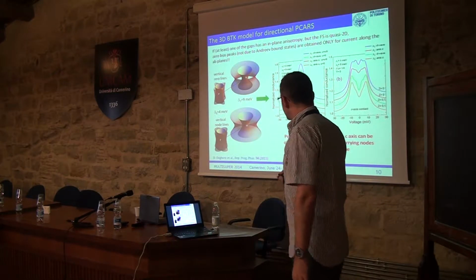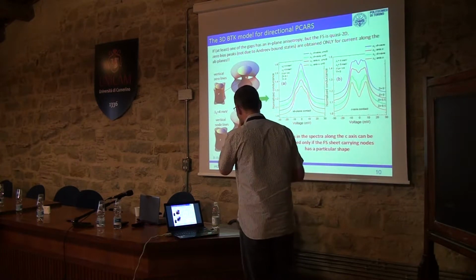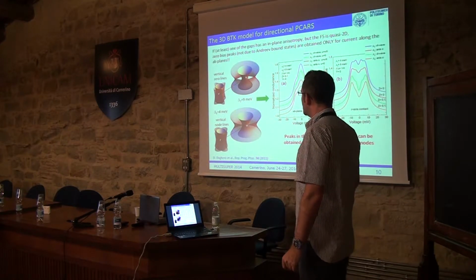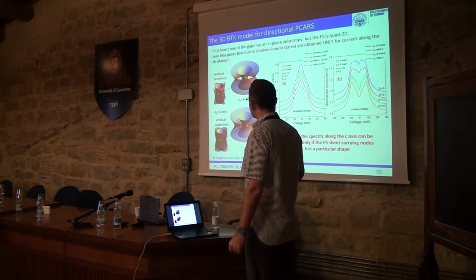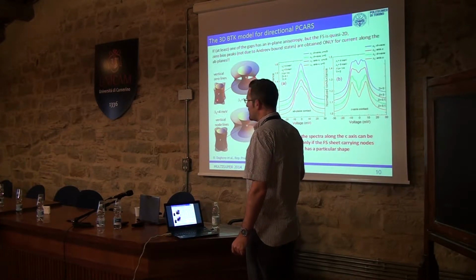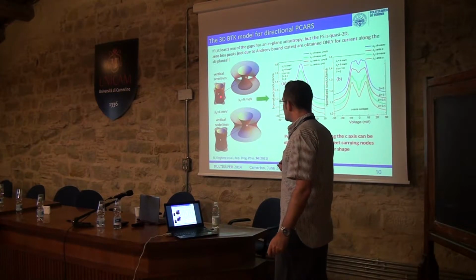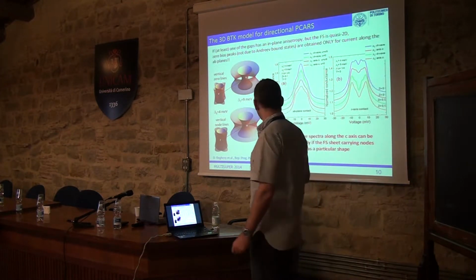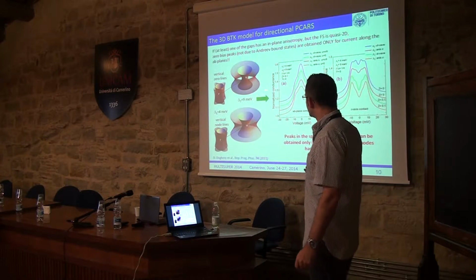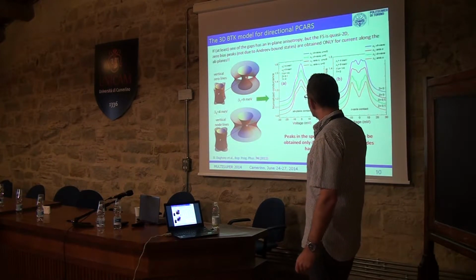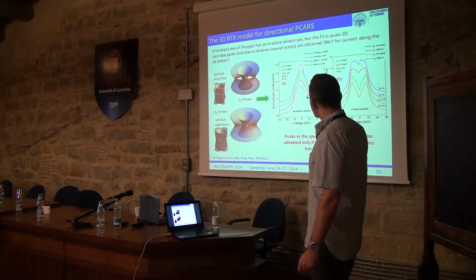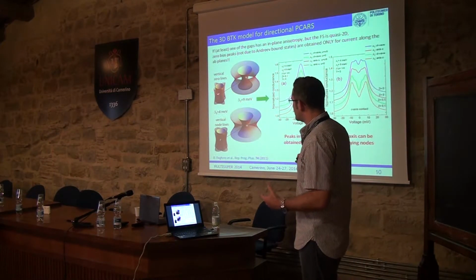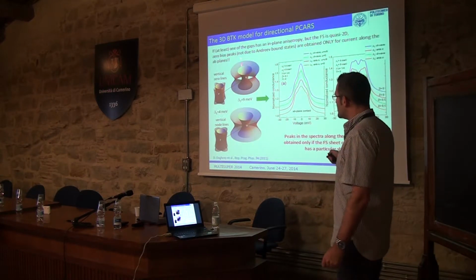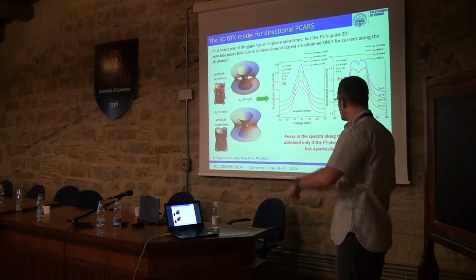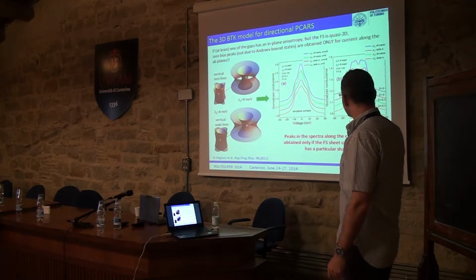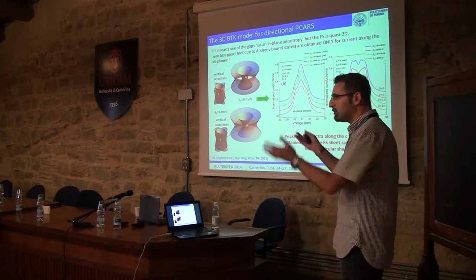One thing that I would like to remark is that suppose that you have two Fermi surfaces like this one, and suppose that you have a gap that resides on this Fermi surface, which is almost 2D, and that has vertical lines of nodes. In this case, if you use the 3D BTK model, you see that for injection along the ab plane, you will see a zero bias maximum. The zero bias maximum is the hallmark of this in-plane anisotropy of the gap. But if you inject the current vertically, that means along the c direction, you don't see a zero bias maximum, but a zero bias minimum. This is an effect of the shape of the Fermi surface.